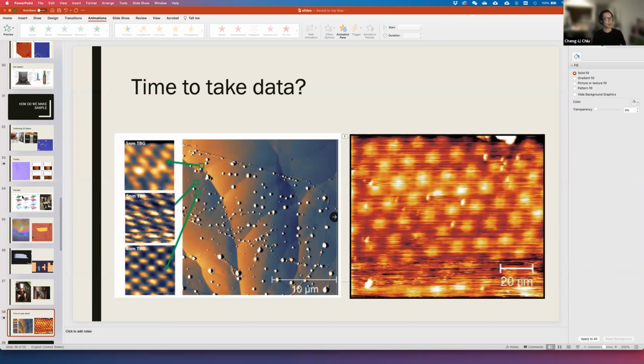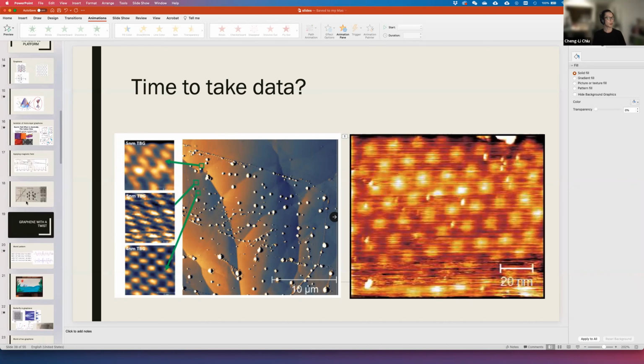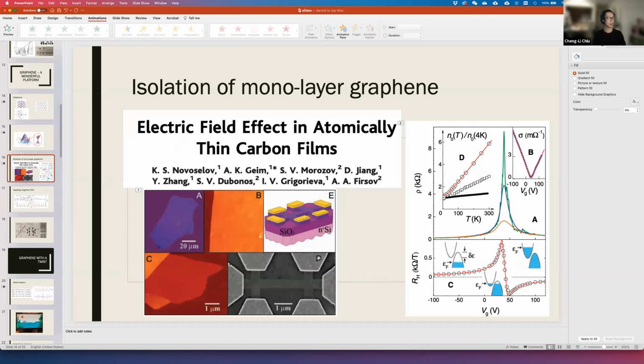Yeah, it's a good question. So let me see. In the very beginning, when people just started to do the experiment, they put it on silicon oxide. Silicon oxide is clean, but it's actually not electronically clean. There are a lot of impurities buried inside the silicon oxide. So you will have a lot of local doping, making your sample behave poorly. So people were thinking about how to get rid of the silicon oxide, making the sample more pristine. One way people first thought of is suspending the graphene, basically doing some fabrication and making your graphene suspended in the air. However, that's also not good enough because it becomes very far away from the gate. So it becomes harder to gate.